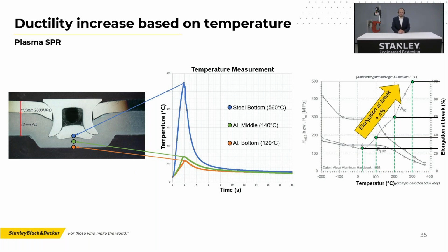You can see here on the left side that the bottom of the steel was 560 degrees. The middle of the aluminum part is 140, yes, 140, and the part on the bottom 120. Thank you. Maybe I need glasses, I don't know, or we need a bigger screen. So yes, we can transport the heat down, and you can see that already with the difference between room temperature 20 degrees to 140 degrees.